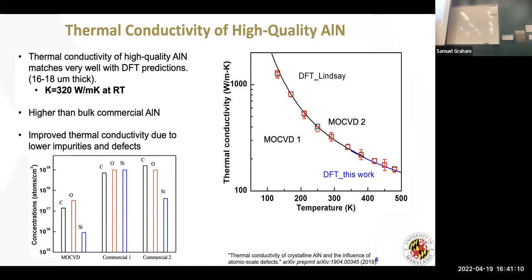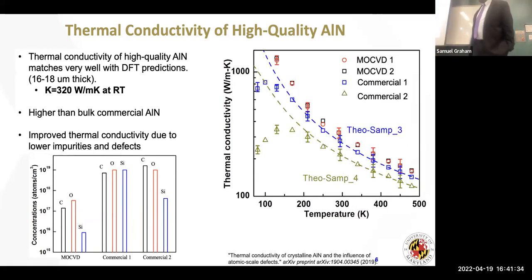And so when you look at this, what was really nice is that when we did these measurements, Lucas Lindsay at Oak Ridge National Labs had done DFT calculations. And the very first time we took our data and put it on top of the DFT calculations, it matched. And these DFT calculations right here are from Tim Feld at Notre Dame. And so 2 different calculations show that this is what you would expect for high purity aluminum nitride. Our experiments follow right on top. There's nothing else in the literature that's ever been measured that shows that.